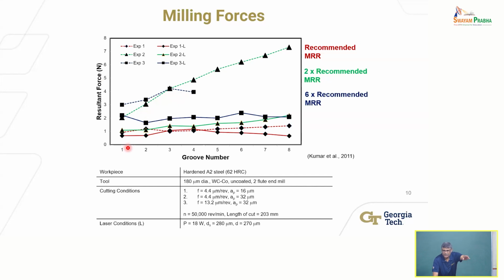So we were cutting grooves in this A2 tool steel of 62 Rockwell C. The tool is a 180 micron diameter tool. It's uncoated. It's a 2-flute end mill. And these are the conditions. There are 3 conditions. That's why you see experiment 1, 2, and 3. This is without a laser, and -L represents with laser assist. The laser parameters are shown here. It's 18 watts. The spot size is 280 microns, and D is the diameter. The distance in front of the tool is about 270 microns. These are optimized with some experimentation and modeling.